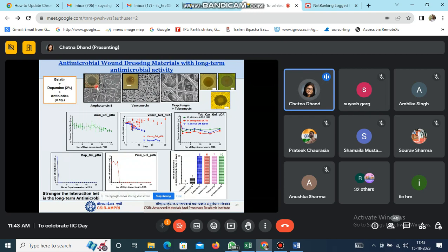So what it actually indicates, I will just explain briefly. In the center, you can see this area is very clean. Outside there's this yellow component. So what is this yellow component? This is basically bacteria. So what we did, we grew the bacteria and put our dressings in the middle. After 24 hours, if we have this clean zone, that means the material is antimicrobial in nature.